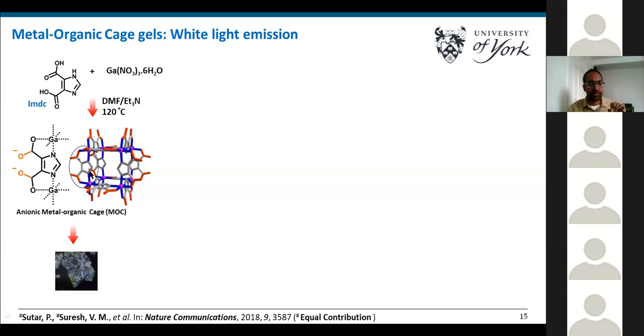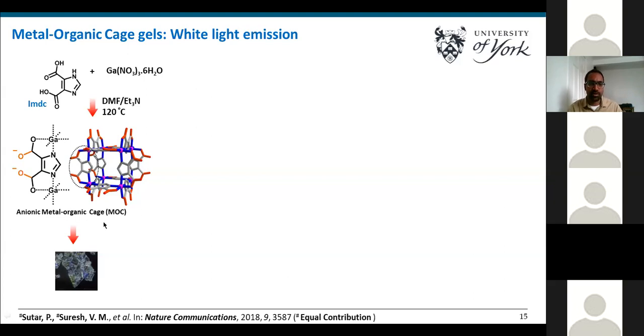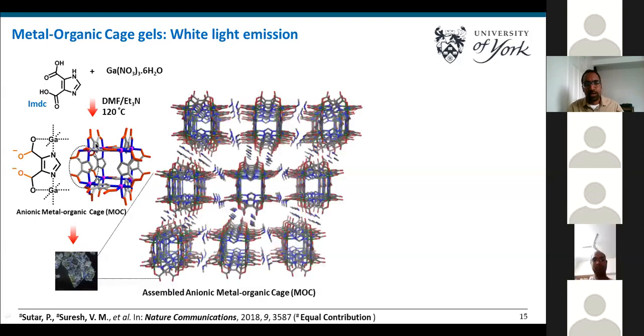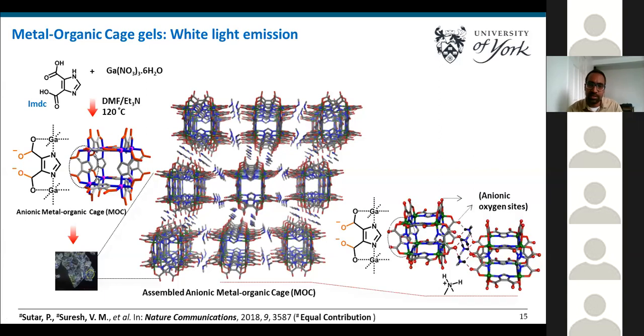So in this cube, there are 12 IMDC units occupying the edges and connecting 8 gallium centers and forming a symmetrical cube-like or cage-like structure, which is termed as metal organic cage or MOC in the next slides. In the crystal structure, we see a large number of cubes assembled in a 3-dimensional framework-like structure. Here, each cube is connected through dimethyl ammonium cations through hydrogen bonding interactions. So the dimethyl ammonium cation is extending these metal organic cages in a 3-dimensional way to form a framework-like structure. And the pores of this framework are filled by water or DMF molecules.